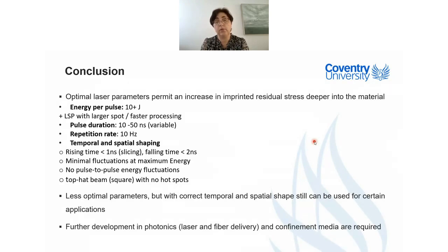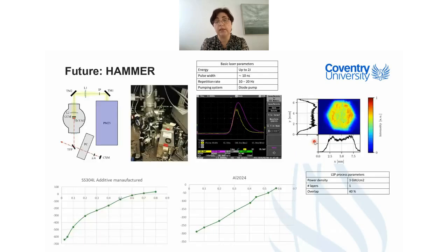Then I think what is really important is the temporal and spatial shaping, and I wrote here a rising time shorter than 1 nanosecond, and a falling time less than 2 nanoseconds. You need to have minimal fluctuation of the energy at the maximum. You should have no pulse-to-pulse energy fluctuation if possible. And the top-hat square beam gives you a lot of opportunity to better define your sequences. But still, as you see, even with less optimal laser parameters, if you do proper temporal and spatial shaping, you can still find applications where you can benefit from using laser shock peening.